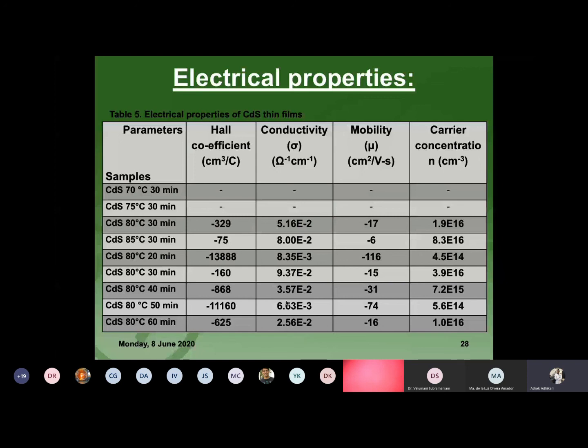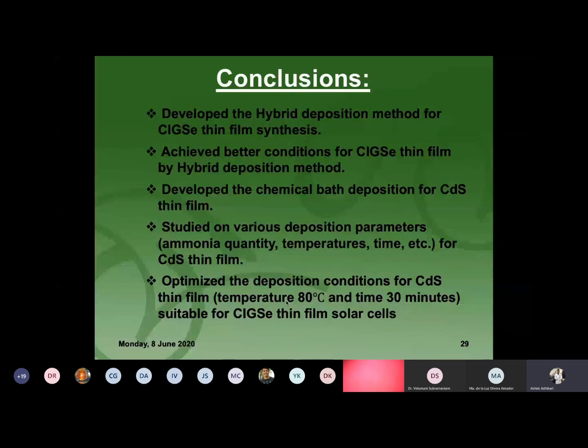So we conclude that we have developed the deposition method for the CIGSe absorber layer, and also developed chemical deposition for CdS thin film in our lab, studying different conditions. Finally we optimized the CdS thin film with the condition of 80 degrees, which showed better suitable thickness, structural, morphological, optical, and electrical properties suitable for use in thin film solar cells as a buffer layer.